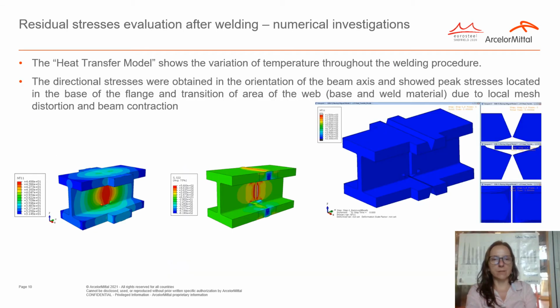The heat transfer model shows the variation of temperature throughout the welding procedure. The directional stresses were obtained in the orientation of the beam axis and show peak stresses located in the base of the flange and transition area of the web base and weld material due to local mesh distortion and beam contraction.